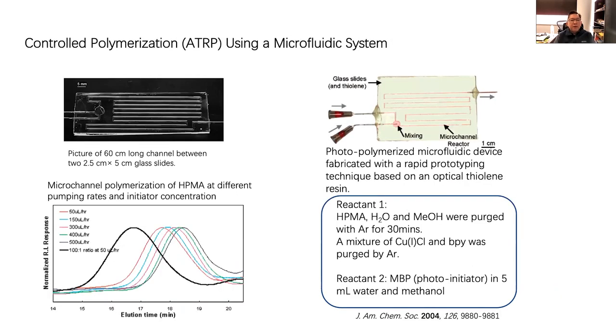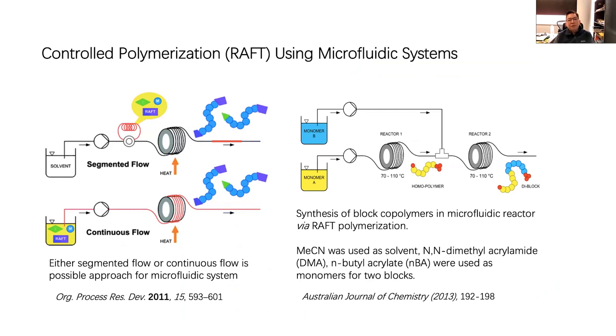Here is an example of an ATRP done using a microfluidic system. Again, by controlling the flow rate, one can achieve a higher molecular weight with a slower flow rate, as observed in this GPC trace. Here is an example of a RAFT polymerization producing a block copolymer, again, based on continuous flow chemistry with either segmented or continuous flow conditions. And this has been, of course, reported way back. So the introduction of the monomer is in sequence. First, introducing monomer A, followed by monomer B, and you can even alternate or introduce monomer C. And that is the advantage of a microfluidic or continuous flow reaction in that you can have sequence control.